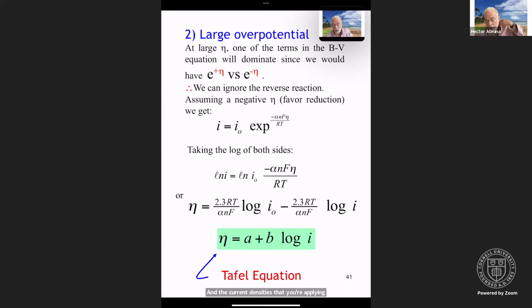So that was a small overpotential. Obviously, if we go small, we can go big. So what are the consequences? Remember that in the Butler-Volmer, we have two components, the cathodic or reductive, the anodic or oxidative. If we make eta large, remember eta has a sign, eta is either positive or negative. If we do that, then one of those two terms is going to drop off because we're having e to a big negative number versus e to a big positive number. So one of those terms will drop because it will become insignificant relative to the other. That's the case, and we can ignore the reverse reaction.